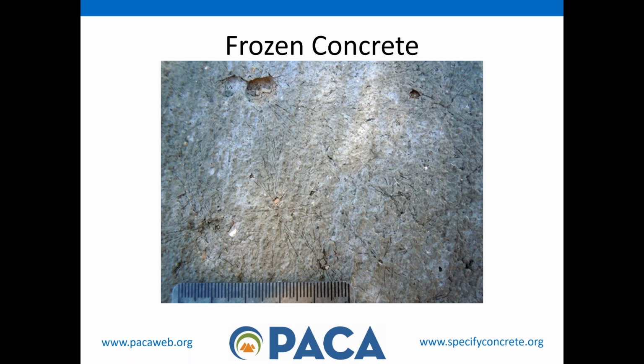Second telltale sign of concrete being frozen is a very, very white appearance, white like a sheet of paper. Here you see a little bit of that white along with the telltale signs, excuse me folks, of that kind of cracking, dried leaf kind of pattern that's going on right there. Not all the concrete froze. You see on the edges it didn't freeze, but you got one frozen spot right there. It's white, and you see the cracking pattern in it. You also see a lot of cracks that look like plastic shrinkage cracks going through it. That's very common. It's a very telltale sign of it because in the wintertime, when the weather's cold, we drive the moisture out of that concrete really quickly, way too quickly.